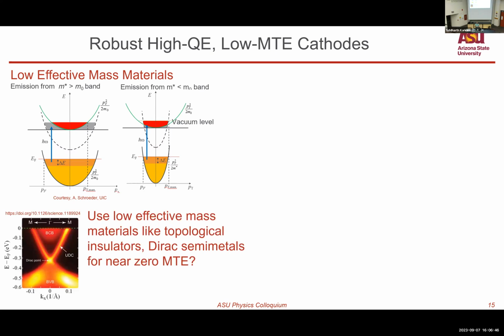There are some very interesting materials, Dirac semi-metals or topological insulators, which have a Dirac point, which means the electron mass at that point is really zero. You have extremely sharp bands. And if we are able to emit electrons only from that Dirac point, we can get very small mean transverse energies, even at room temperatures. And some of these materials, topological insulators, are thought to be quite robust. So that could also solve our vacuum problem.